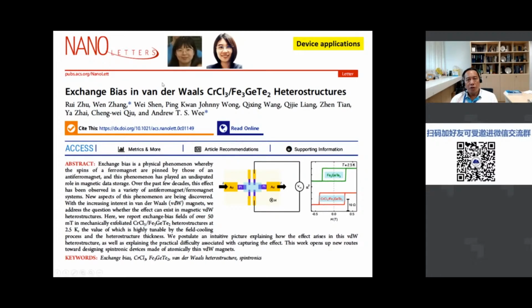So we're studying chromium trichloride FGT heterostructures. And it's interesting because, as this table of contents image shows, if we have this system of CrCl3 on FGT, the hysteresis loop shifts relative to the vertical axis, as opposed to the FGT where it's symmetric, right? So this shift is known as the exchange bias. This exchange bias is a physical phenomenon whereby the spins of a ferromagnet are pinned by those of an anti-ferromagnet. And this is essentially the effect that underpins our magnetic data storage that we use today. Hence, this is very important.